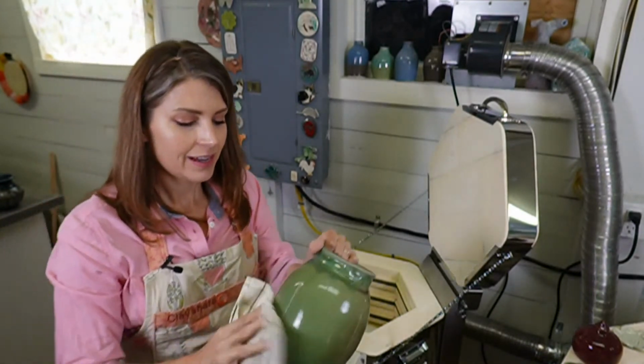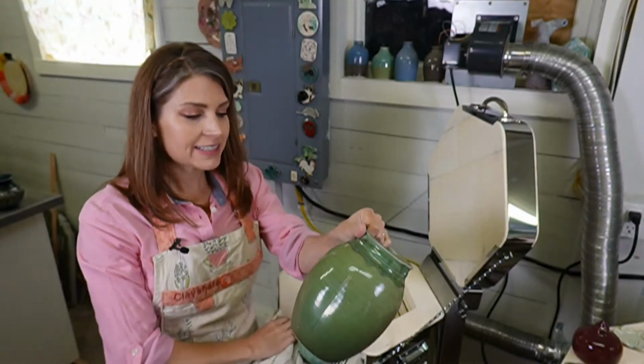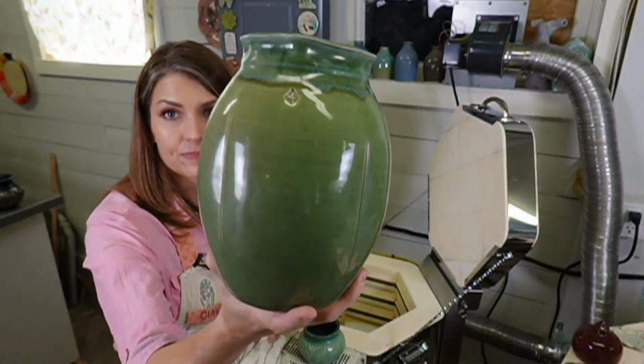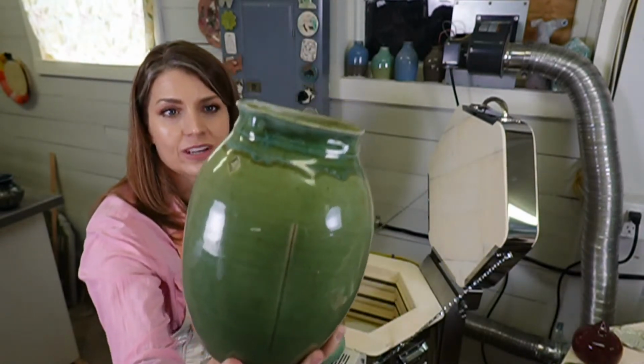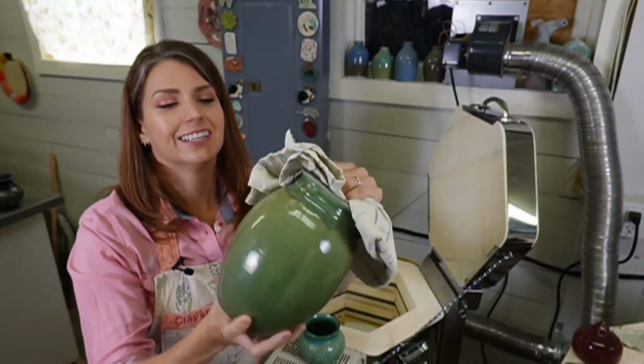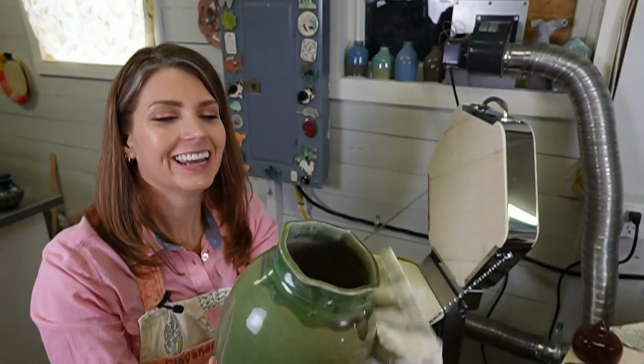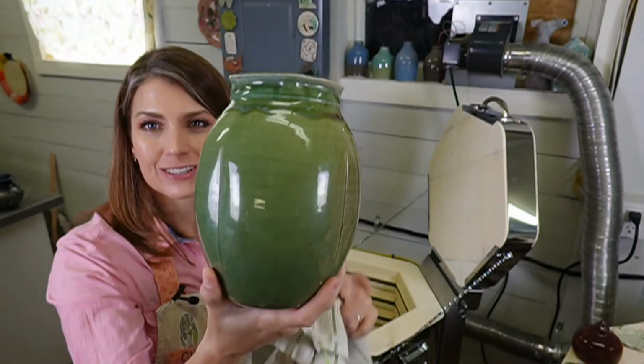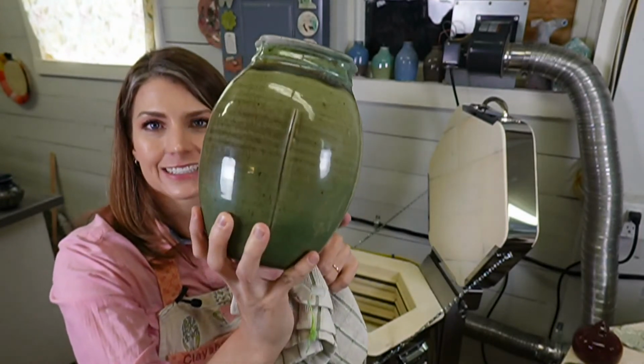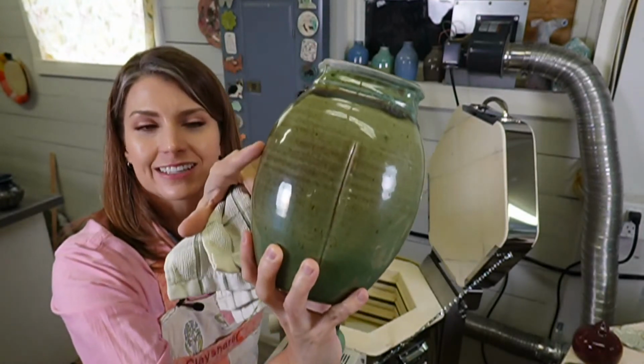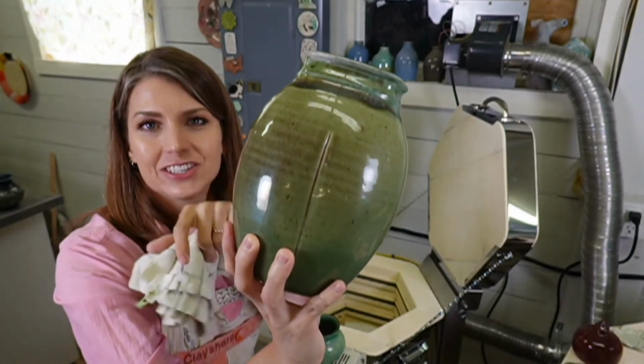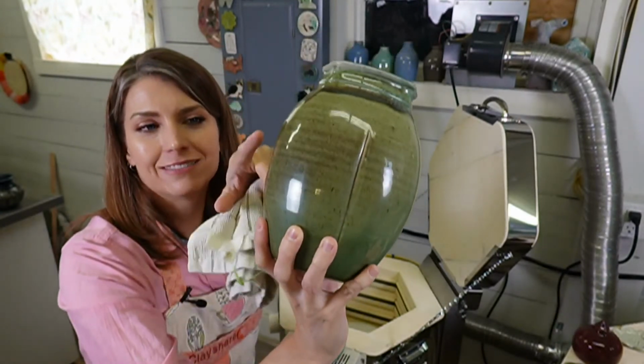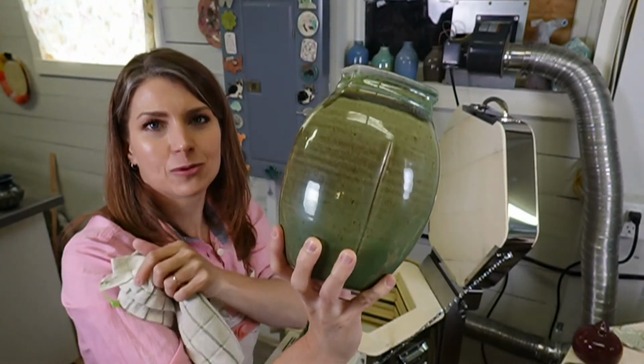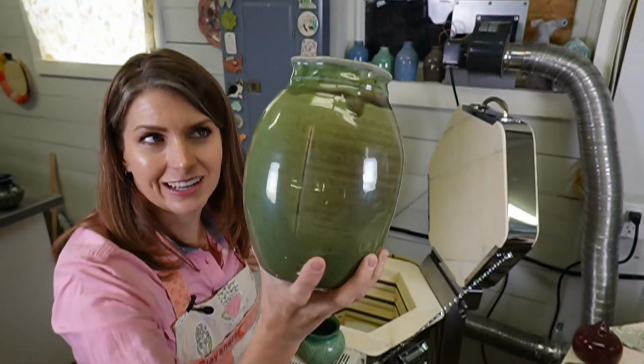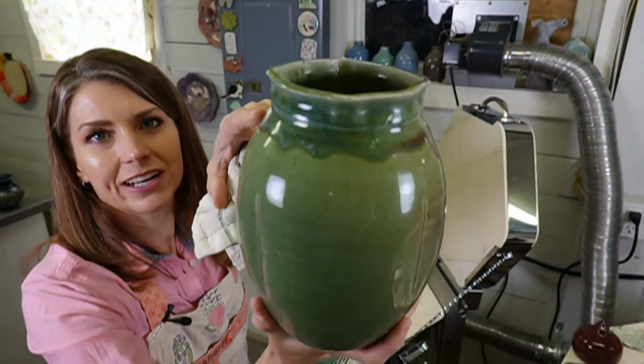Thanks. So this is that glaze. This is my Oribe. Here it is at cone 10. A very dusty cone 10. And ooh, that's nice. That's where it was near the edge of the gas kiln, and so we have a little more of the flame, a little more reduction happening over there. And then this right up here on the top.